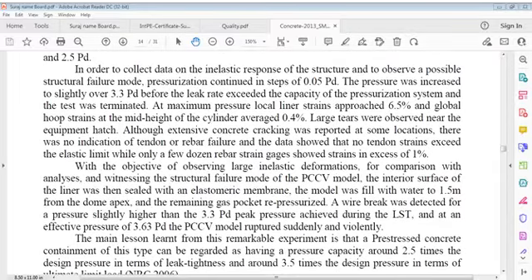In order to collect data on the inelastic response of the structure and to observe a possible structural failure mode, pressurization continued in steps of 0.05 PD. Pressure was increased to slightly over 3.3 PD before the leak rate exceeded the capacity of the pressurization system and the test was terminated.